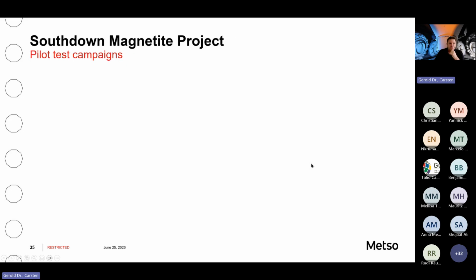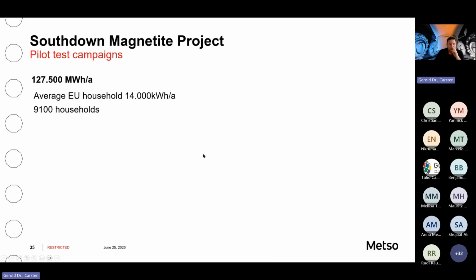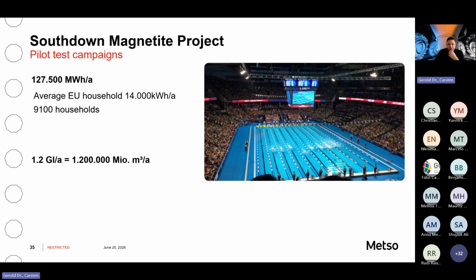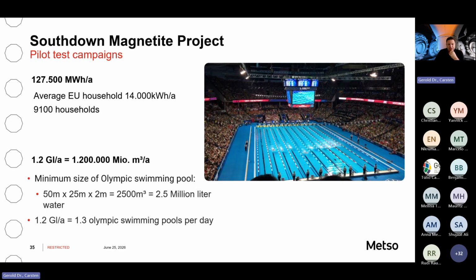And to visualize that a little bit, 127,000 megawatt hours is about the energy consumption of 9,100 average households in the EU. And when you consider the water amount, that's about 1.3 Olympic swimming pools per day of water that you save. And surely for areas like Australia, Chile, Peru, Southern Africa, Northern Africa, where water is critical, this can have a massive impact on your project economics. And also in getting it running at all.